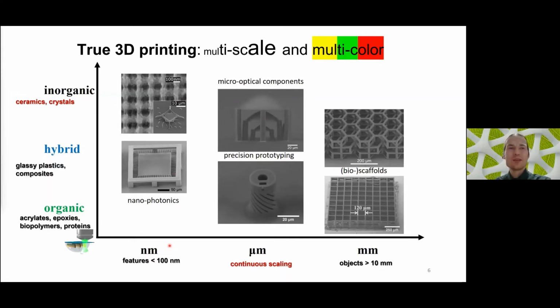So the technique enables making features smaller than hundreds of nanometers, while the overall object size can reach more than tens of millimeters, up to centimeters nowadays. And it's a continuous scaling, so it does not have strict limitations. By changing focusing optics and adjusting laser power, we can have all scales in between. And from the material point of view, all kinds of organic resins can be processed, whether acrylates, epoxies, vinyls, some biopolymers, and even proteins, which can be cross-linked.